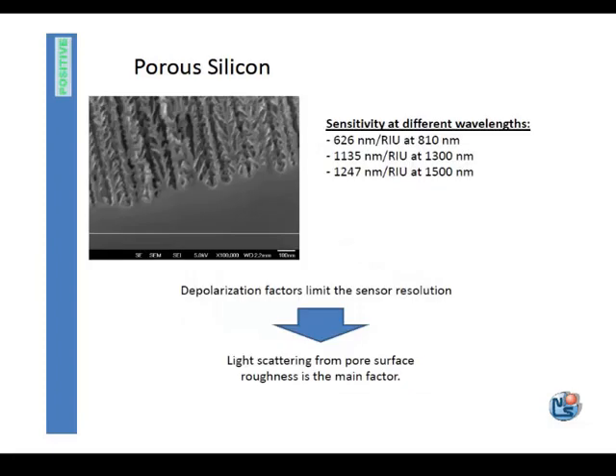So we start to do the optical analysis of our sample. This is a cross-sectional image of a porous silicon layer. You see the pores grow mainly along the 100 direction, and in our first experiment, they are heavily branched. Nevertheless, we checked the sensitivity of this type of device, and we noticed a very large sensitivity. For example, at 1.5 micron, we get a sensitivity of 1.2 micron per refractive index unit. That means that if your refractive index changes by a single unit, your spectra will be shifted by 1,247 nanometers. This is a huge value, comparable with photonic crystal nanocavities and also surface plasmon resonance methods.